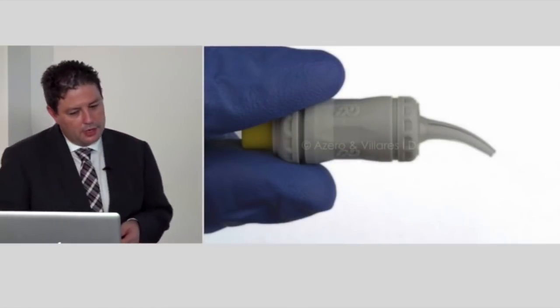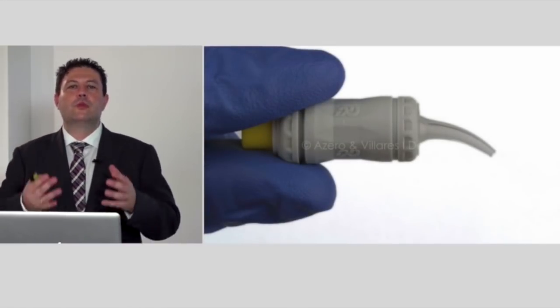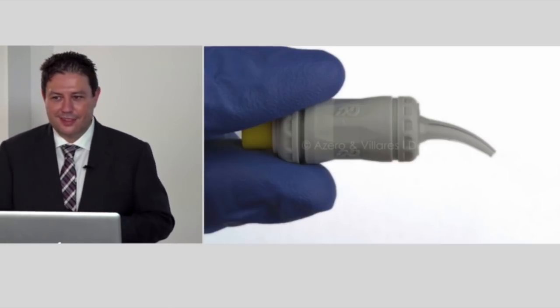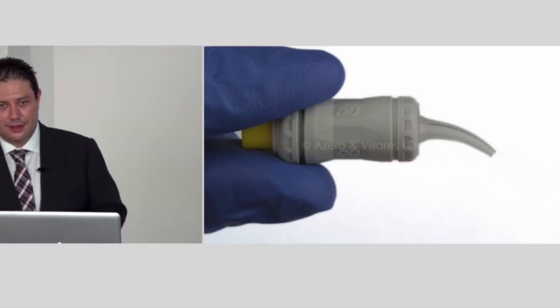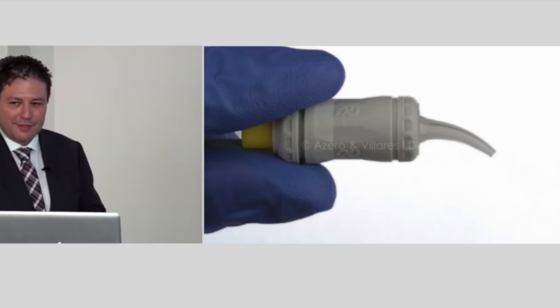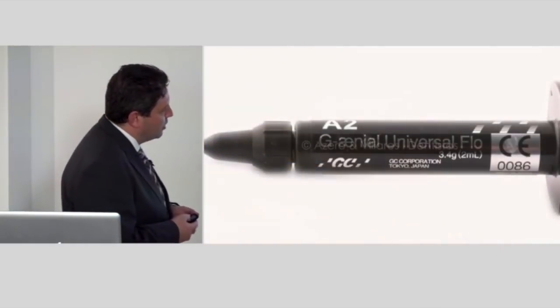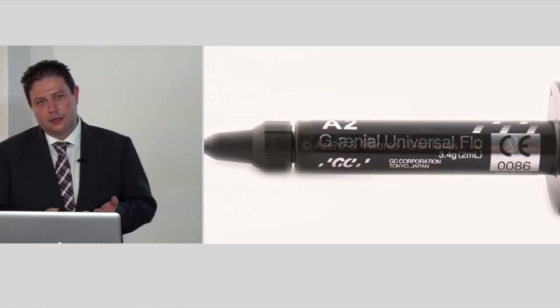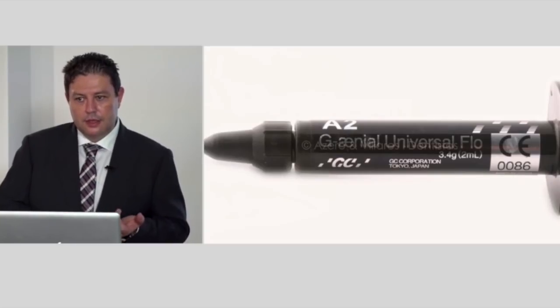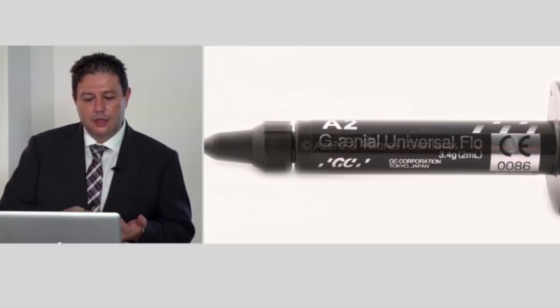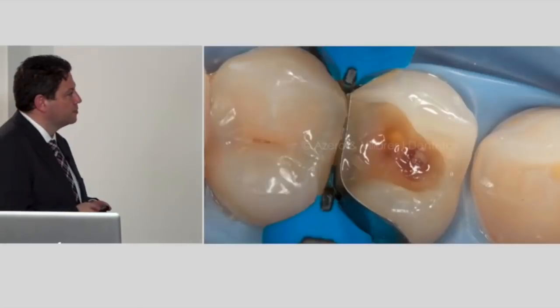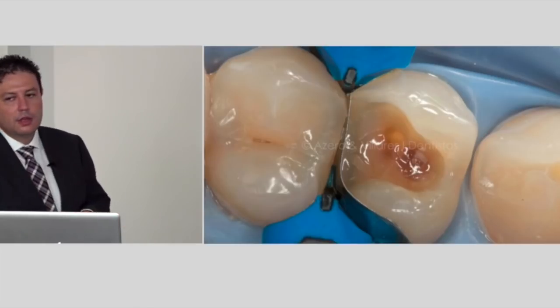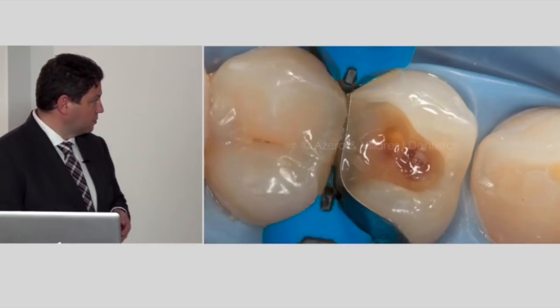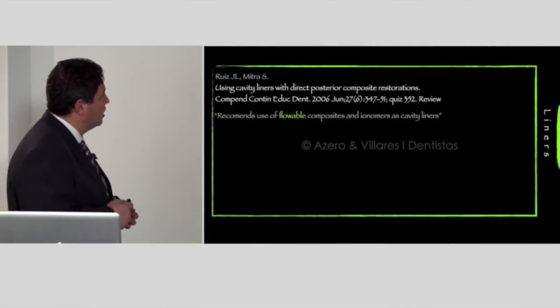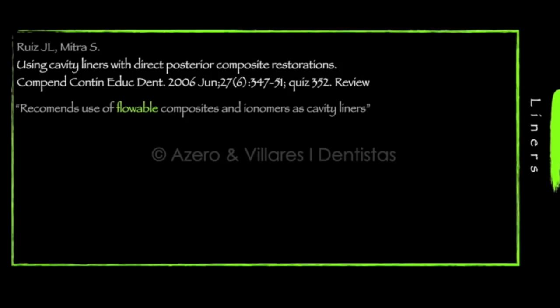Now the use of glass ionomer is increasing because now we're doing more prevention than being destructive. We were eliminating so much tooth in the past, and now we know that if we don't eliminate, we will have better results. And about the flowable composite resin, what we need is a good material to put in place that doesn't have so many bubbles and gives a good result. We put only a very small layer of flowable composite resin, and if we follow the literature, classic articles recommend the use of flowable composites and ionomers as cavity liners.